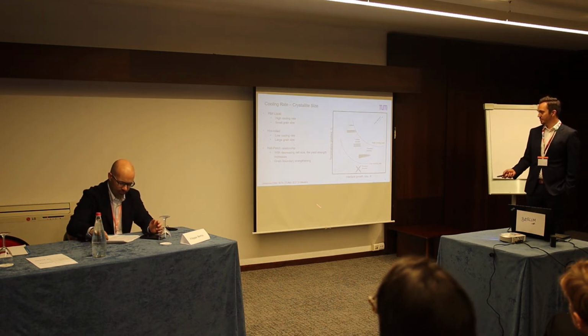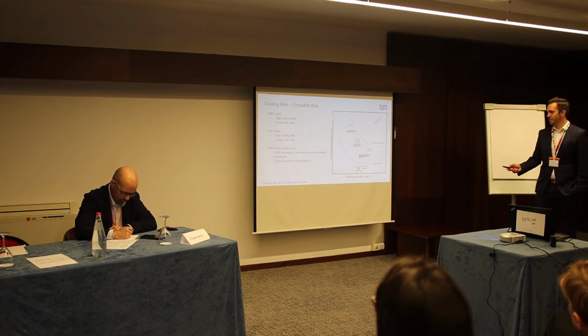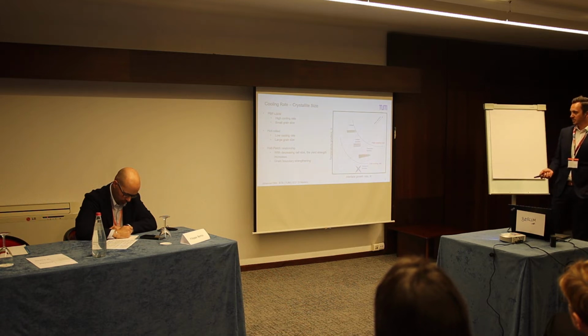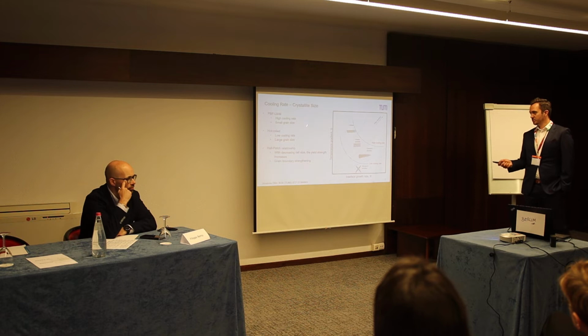So let's take a look at the cooling rate, or basically at this graph here on the right side. You can see on the x-axis the interface growth rate and the temperature gradient G. And the product of these two is the cooling rate. For PBF-LB we have a very high cooling rate, resulting in a smaller grain size, because the product of these two, as I said before, defines the cell size. Compared to that, the hot rolled 316L has a lower cooling rate and therefore also a larger grain size.